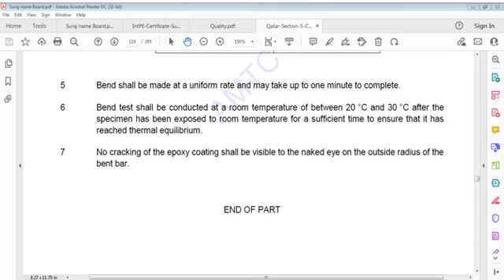Bend shall be made at a uniform rate and may take up to 1 minute to complete. Bend test shall be conducted at a room temperature between 20 degrees Celsius and 30 degrees Celsius after the specimen has been exposed to room temperature for a sufficient time to ensure that it has reached thermal equilibrium. No cracking of epoxy coating shall be visible to eyes on outside radii of bent bar.